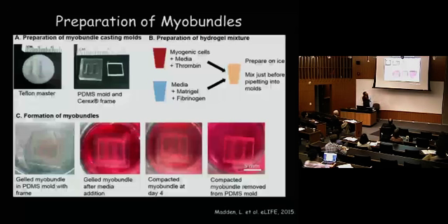And then we will dissociate these cells that I've shown from the muscle biopsy, expand them, get a lot of cells, mix them with a hydrogel, and the hydrogel is a three-dimensional matrix. It is very much similar, in essence, to a blood clot. So this is the same material that you find in a blood clot. It's called fibrin, right? And then you can use these cells, mix them together, put them in these kind of molds,